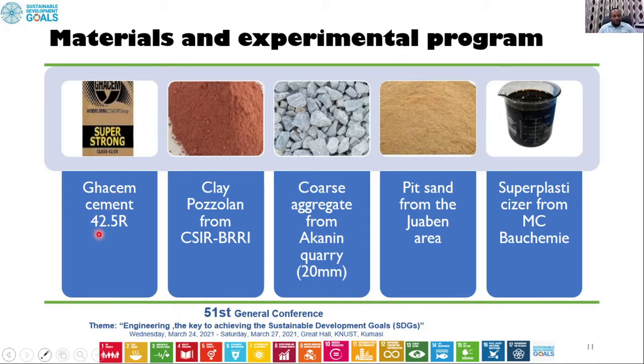Ghacem cement 42.5R. The Pozzolan was obtained from BRI, coarse aggregate from the Akanin quarry. Pit sand was used and we obtained it from the Juaben area. And this is superplasticizer, which is not common in the concrete we use in Ghana. So we call it a high range water reducer. It is a game changer. It changes the properties of concrete. It enhances the strength and the chemistry of the concrete.